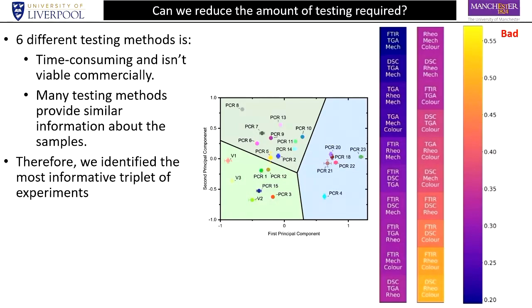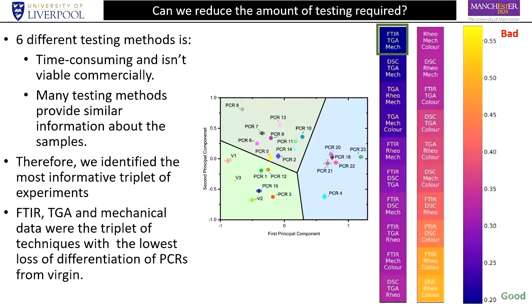So if we've got a yellow color, we're not really able to use those combinations of tests very effectively. But the great thing is, these 3 tests, FTIR, thermogravimetric analysis, and mechanical tests, are quite widely used in most plastics recycling companies, and they're quite available tests generally. So actually, we found that these 3 tests allow us to attain about 80% of the same data as all 6. So really powerful selection. So that's a key thing, and again, that's something we're working on developing forward.